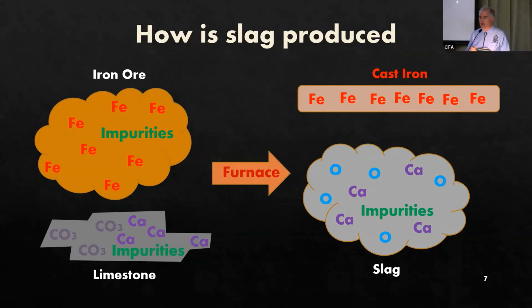And that's where the second ingredient, limestone, comes in. From the melting of the limestone and the burning of the charcoal, you can reduce the iron, taking it back to its native state. And that produces iron metal, which after all is the product that's sought from a furnace. And then the impurities that were originally present in the iron ore become more attracted to the limestone than they are to the iron metal. So they leave the furnace in the form of the slag, which you see in this lower right-hand corner.